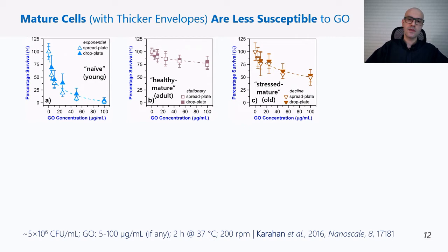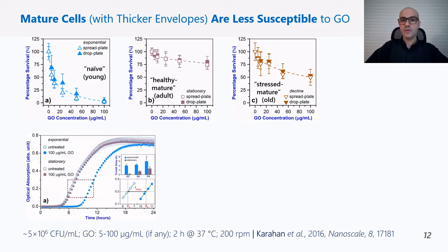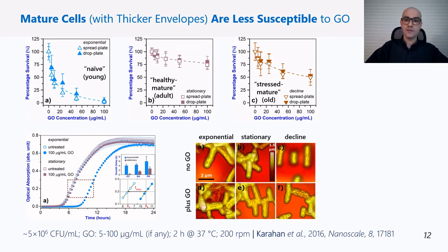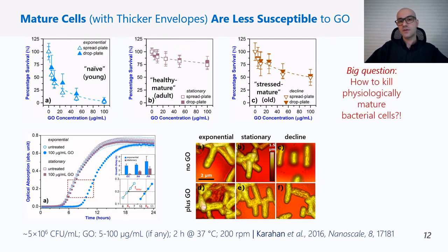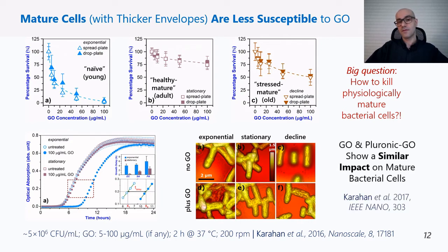Very obviously, young cells die away even at low graphene oxide concentrations. In contrast, mature cells are much more resistant to graphene oxide, and we were able to verify this conclusion with different complementary techniques. So the question was, how to kill those mature cells? Naturally, we tried pluronic graphene oxide mixtures first. It helped a bit on some species, but basically failed.